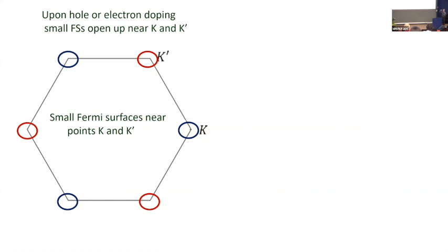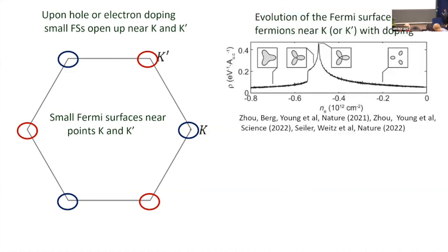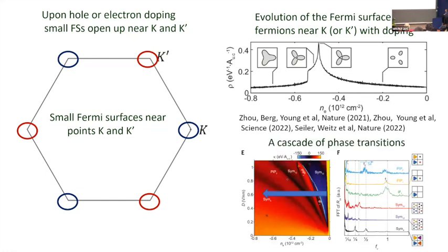To zero approximation, if you open up a small Fermi surface by doping either into the conduction band or the valence band, you open up small Fermi surfaces located near the K and K' Dirac points in the Brillouin zone — two valleys, degenerate by symmetry. The actual situation is more complicated: you open up three small pockets, they merge through a van Hove point, and then you get one larger Fermi surface. Either way, you have fermions with small Fermi surfaces and flat dispersion, so all effects of interaction are enhanced.